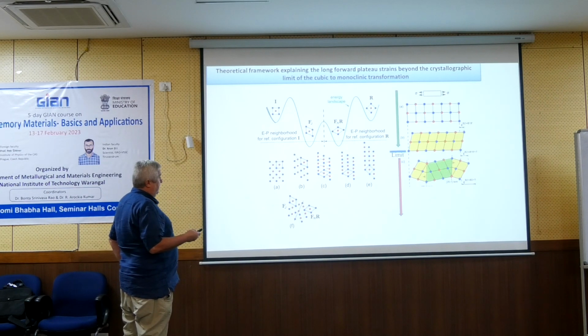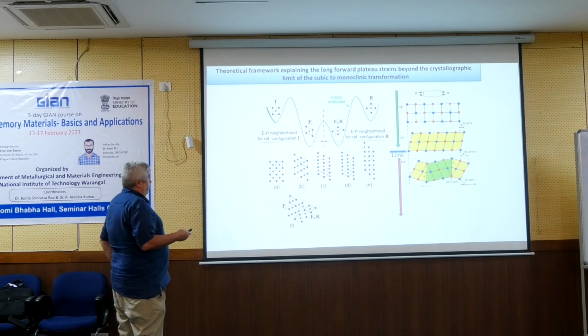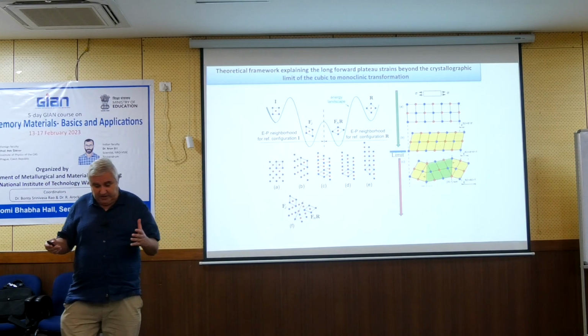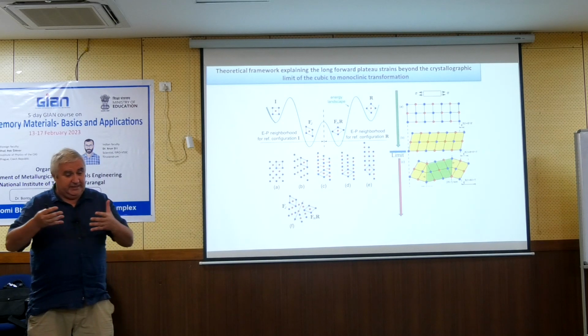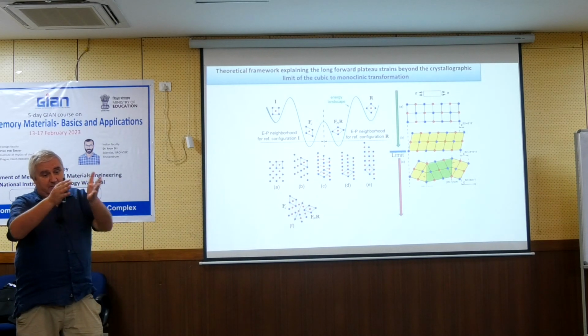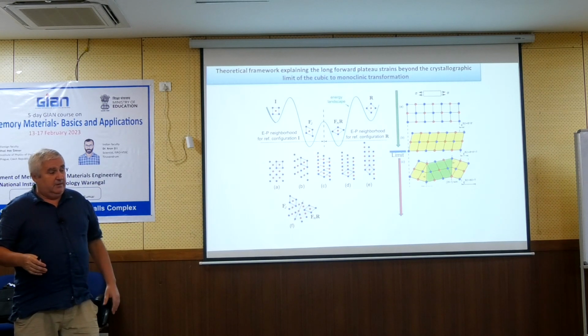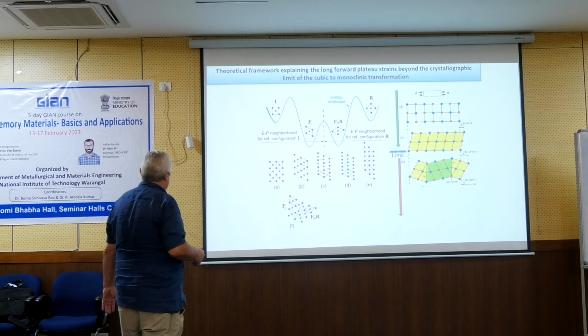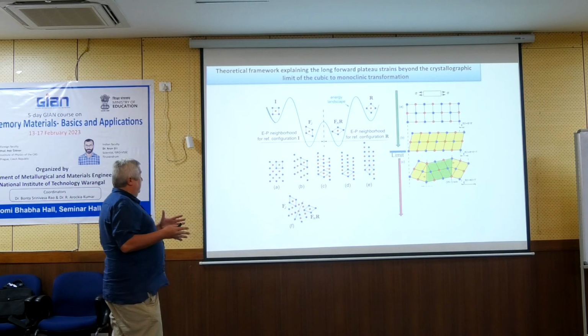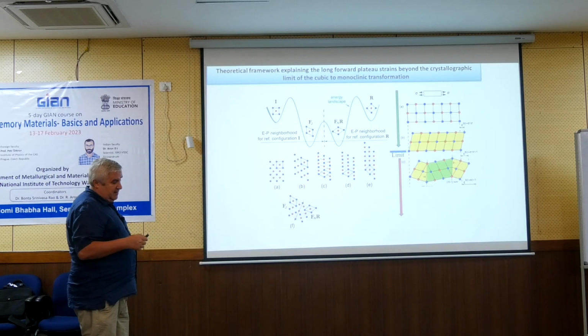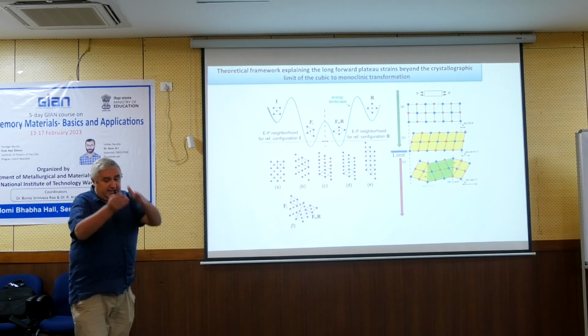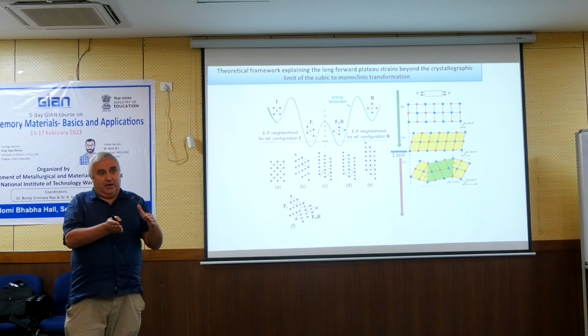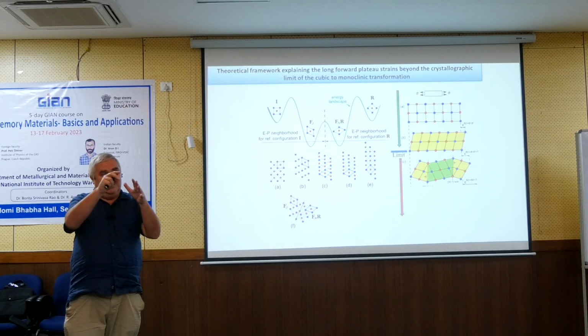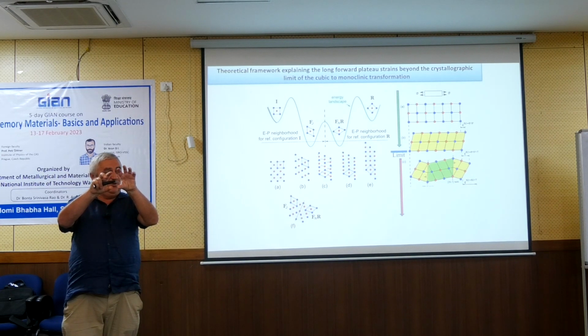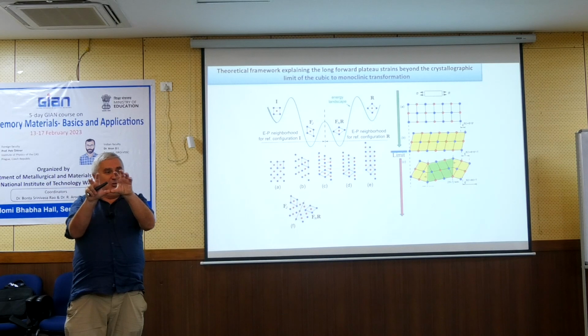Now I should explain why we have this plasticity, because we don't have many dislocations. We didn't see them at 100 Celsius. We have seen mainly these deformation bands. So we came up with an explanation, which recently was in line with the literature evidence: inside these deformation bands, the austenite lattice is not equally oriented as it was before, but it is rotated. So the deformation bands are in fact rotated austenite lattice.